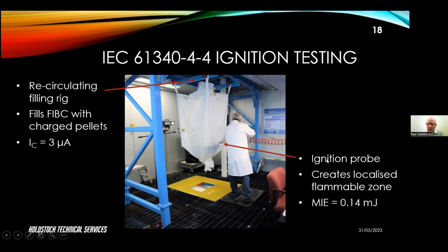And then the operator has an ignition probe which is directing a flow of gas over an earthed electrode, and that creates a localized flammable atmosphere, so that any brush or spark discharge coming from the bag will have to pass through that atmosphere to the earthed electrode. And the gas that we use is actually ethylene, but it's controlled to have a minimum ignition energy of 0.14 millijoule. And that's considered to be the lowest ignition energy of any solvent that's likely to be used in FIBC handling operations.